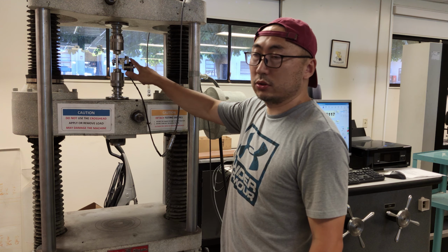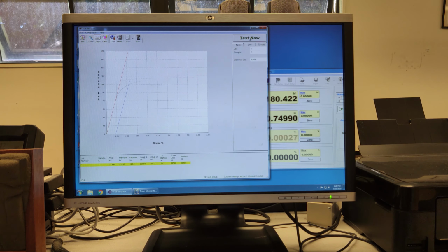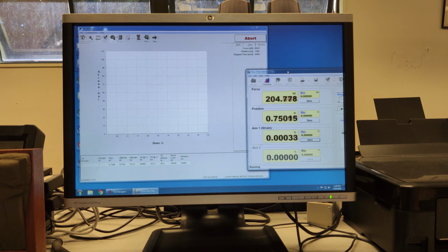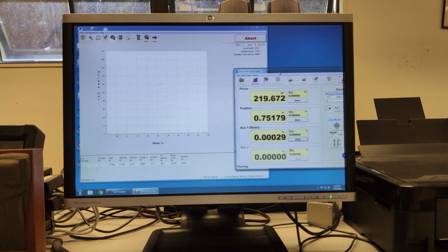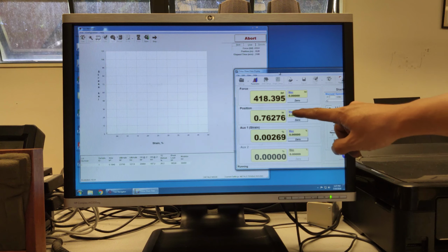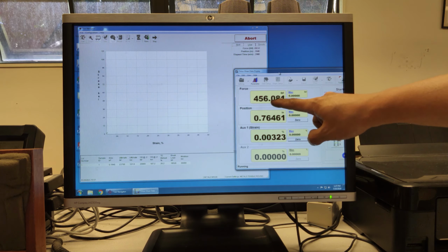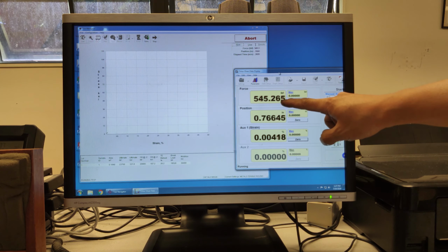After inputting the average diameter into the software, we can run the testing now. By the way, the sample videotaped in this step is a different sample, so the initial load applied was 186 pounds, but all the testing procedure was the same. Also, the testing frame position didn't start from 0. Don't worry, we mainly care about load and strain, which later are converted to the stress-strain curve.